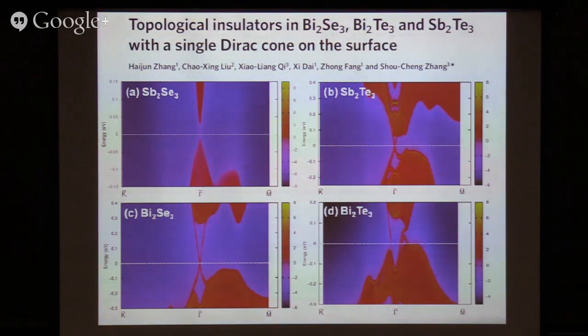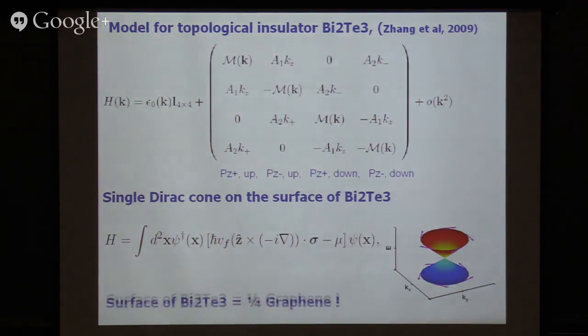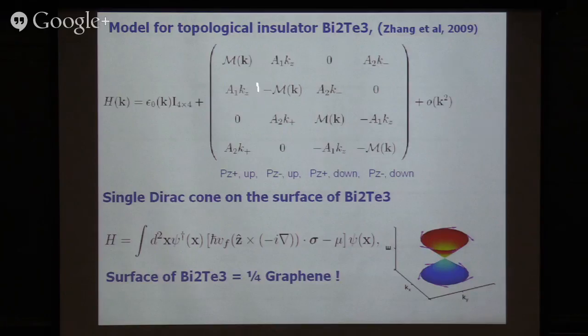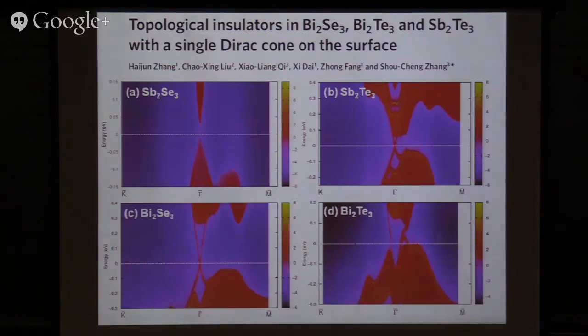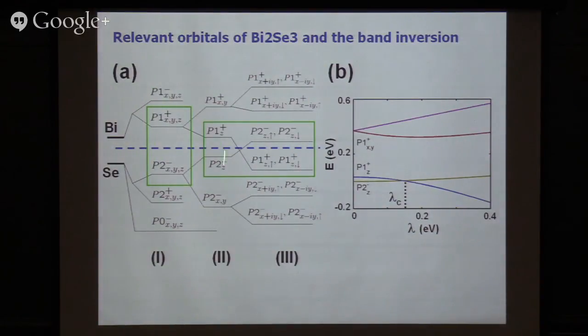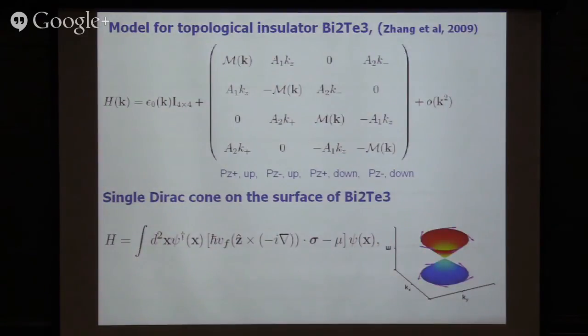And inside, between the conduction band and valence band, which are separated by about 300 millielectron volts, there's a single Dirac cone lying around the gamma point. That effective theory is described by the three-dimensional Dirac equation, where this mass gap labels the energy difference between the bonding and anti-bonding p orbitals. When you dial the spin orbit coupling, there's a band inversion that happens, and it traps some topological surface state.